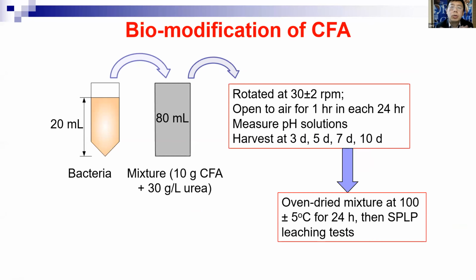And the reason is we don't even add calcium chloride solution in there, because the fly ash has calcium inside, so we can use that calcium ion to see how to modify these leaching behaviors. So this is the procedure: once we add the bacteria in the fly ash, then we add urea solutions.